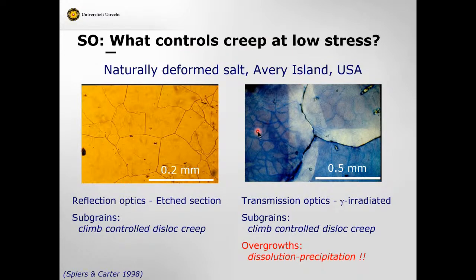Let's go back to nature and actually look at the microscopic structure of some natural salt. This is from Avery Island in the United States. This is deformed naturally, a natural salt tectonic flow, low stresses of a few MPa. Look inside the grains and you see these subgrains. This is evidence of climb-controlled dislocation creep. Using another technique, which Janos Urai pioneered and we did much work on together, by irradiating salt, you can decorate, you deposit sodium on the dislocation structures, and again you see subgrain structures here, but it reveals something else that you don't see in a normal optical microscope or SEM. You see crystal overgrowth.